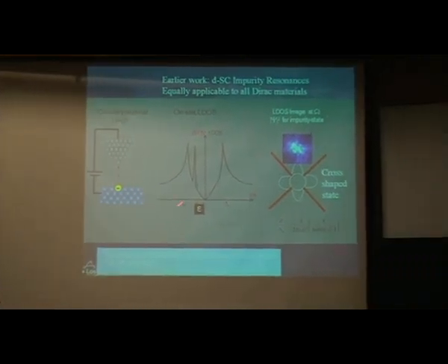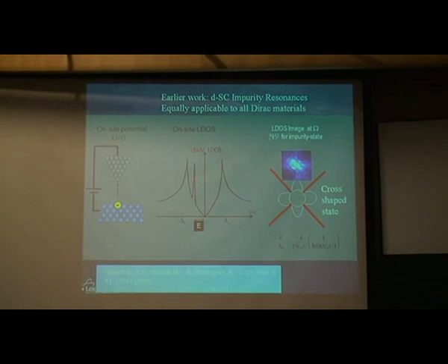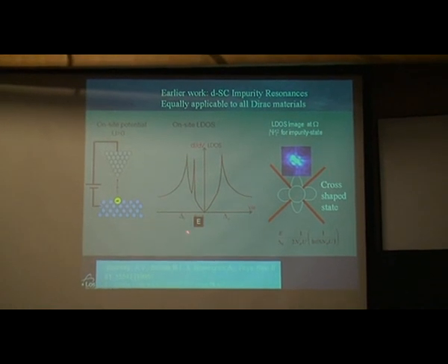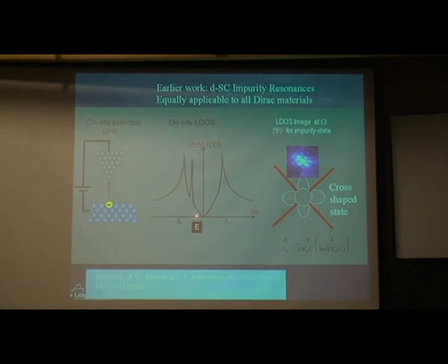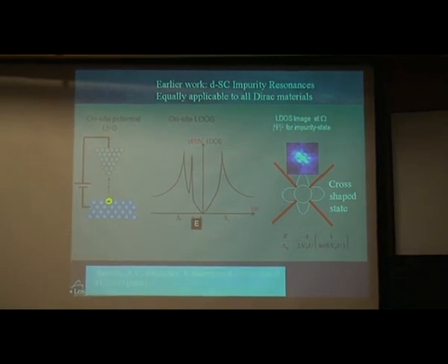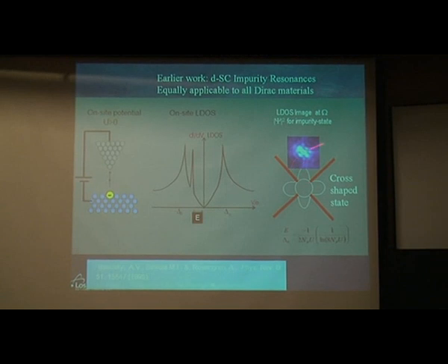observed, namely that electronically you will have impurity resonances inside. And of course, it always plays if you have a sharp contact. So if you have a low density of states to begin with and you have a sharp resonance, you see the sharp, bright features in the tunneling characteristics. Another one is that one can connect the intensity seen in the STM with what is predicted for the pairing state, and maybe one can see if it's a D-wave superconductor or not.